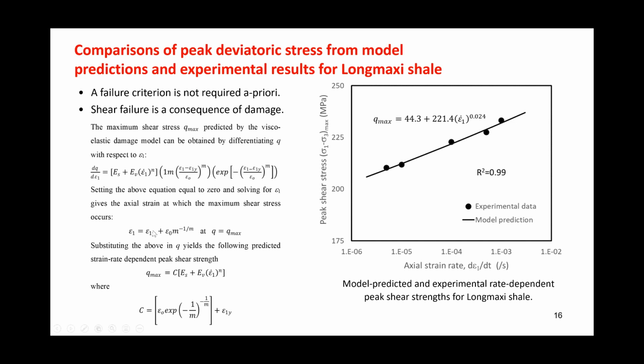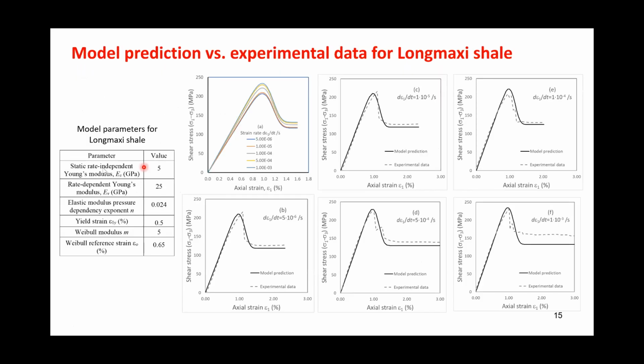Okay, so we can see that it is constant. The peak at maximum shear stress, Q max, is given by this function only of epsilon_y, the reference strain, and the Weibull modulus. And if we put this strain back in the derivative, we get a very simple expression for Q max, which is a function of C, which is just a function of the constant model parameters, and the static and the strain rate dependent Young's modulus. Substituting all the values from this table, by the way, these are the parameters that are required. We only need 6 parameters to represent the model.